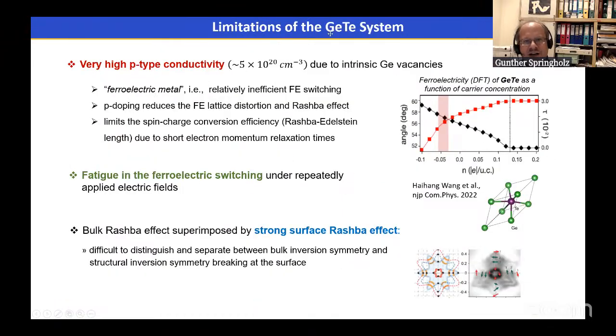Now, germanium telluride is a system which has quite some limitations, and that is due to the fact that germanium telluride has a high density of germanium vacancies in the crystal lattice, and this gives rise to quite a high p-type conductivity of the order of 10 to the 20 per cubic centimeter. So strictly speaking, it's not a ferroelectric semiconductor, but can also be viewed as a ferroelectric metal because the Fermi energy is quite deep in the valence band.